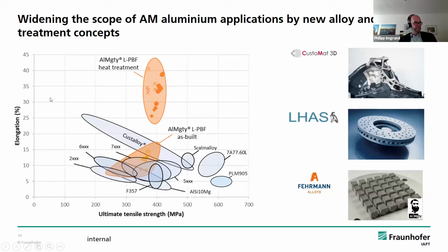Very briefly touching on the story before, aluminum development for additive, starting from the standard aluminum silicon 10 magnesium, which is in a range of, well, 200 to 500 megapascal tensile stress and elongations around maximum of 10 to 15%, very standard. We can go for new alloys like this CustAlloy that I just showed here, which has more flexibility in its mechanical property range.